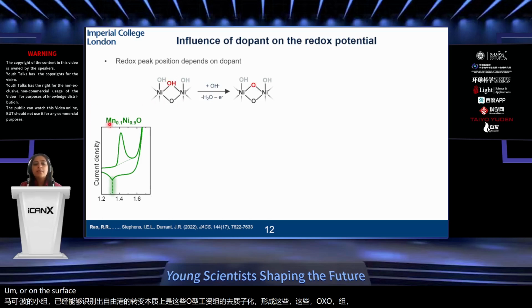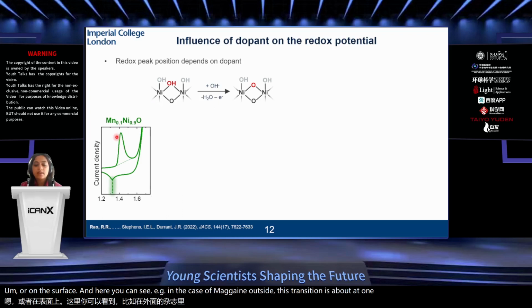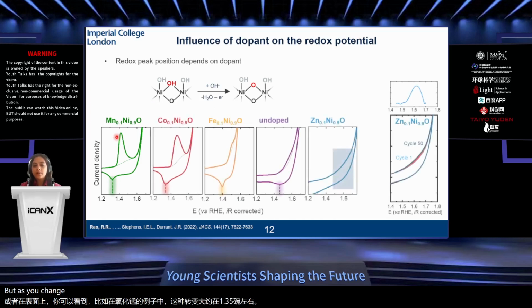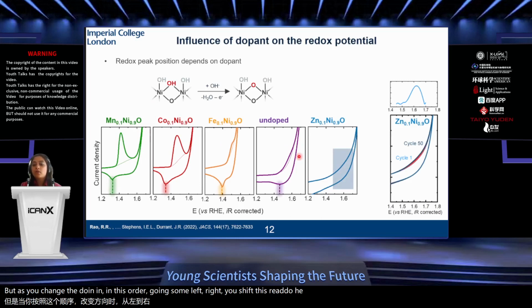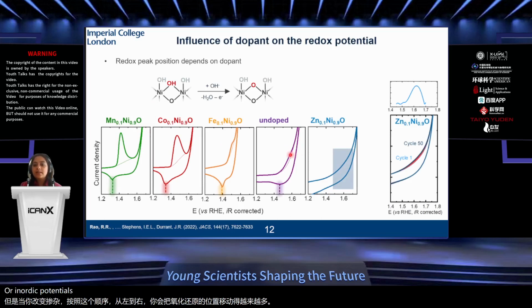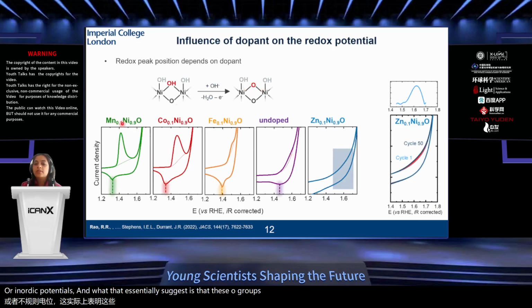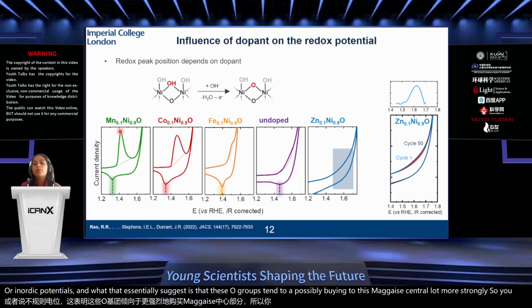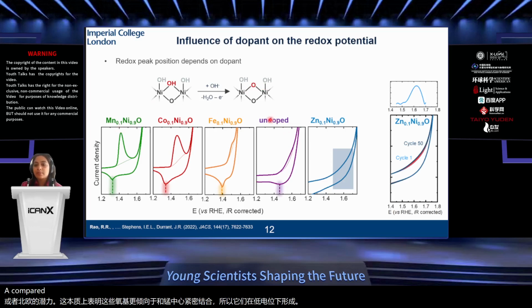And here you can see, for example, in the case of manganese oxide, this transition is at about 1.35 volts or so. But as you change the dopant in this order, going from left to right, you shift this redox peak position to more and more anodic potentials. And what that essentially suggests is that these oxo groups possibly bind to this manganese center a lot more strongly. So you form them at lower potentials compared to, for example, the undoped nickel oxide case.